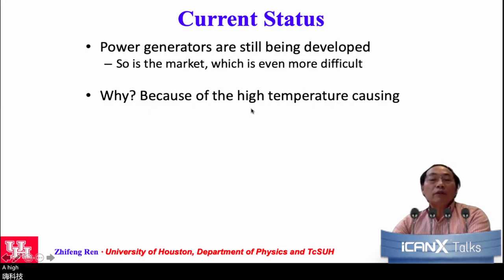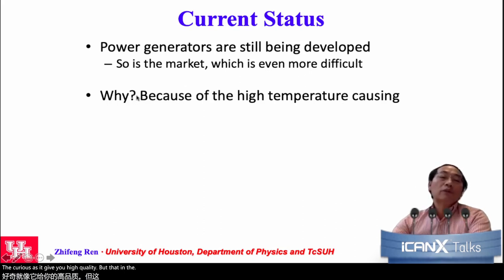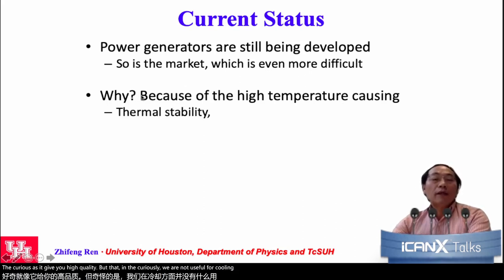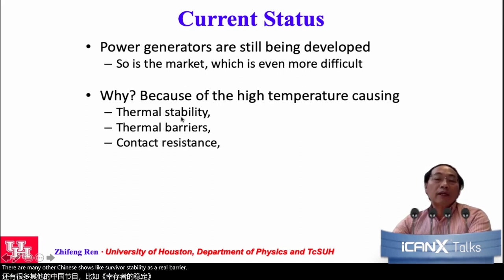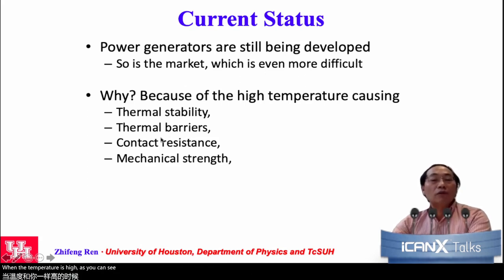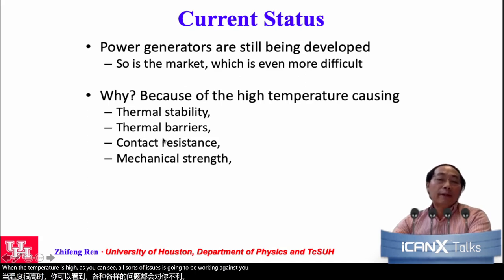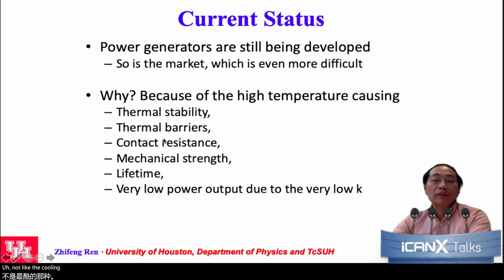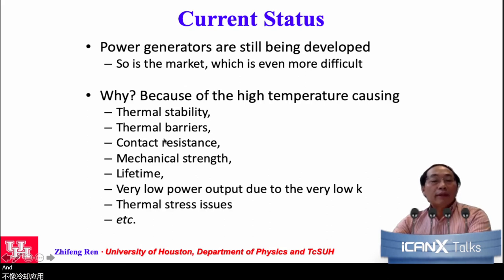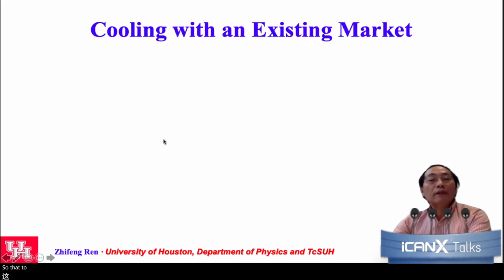And obviously, high temperature materials give you high ZT, but that material is really not useful for cooling. And of course, for power generation at high temperature, there are many other challenging issues like thermal stability, thermal barriers, contact resistance, mechanical strength. When the temperature is high, as you can see, all sorts of issues are going to be working against you, not like the cooling applications, okay? And so that's the current situation.